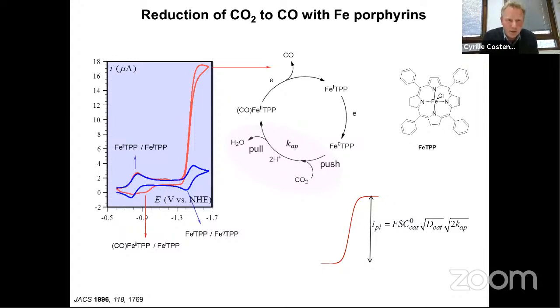And so I think it's a good example to show you how you can use the CV to analyze the mechanism and maybe improve the catalytic process. So here is an example of the CV that you can get in organic solvent. The reason why we use organic solvents is because the solubility of CO2 is very large. So in blue here you have the CV of iron porphyrins, where you have two successive waves.